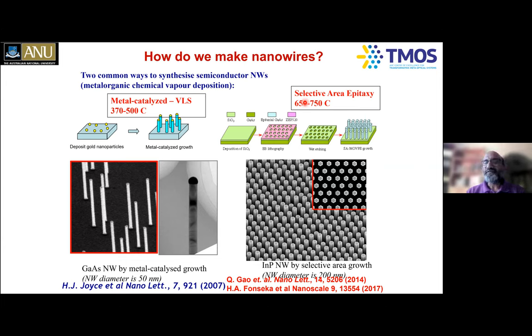In this case, I'm giving an example of indium phosphide. We take an indium phosphide substrate and deposit some silicon dioxide using plasma enhanced chemical vapor deposition, and spin coat the photoresist, and then do electron beam lithography and create patterns of holes. And then you etch through the silicon dioxide so that in these holes, indium phosphide crystal is exposed. Then you put this into the MOCVD reactor and heat it up to somewhere between 650 to 750 degrees Celsius and introduce the gases needed for the growth of indium phosphide, trimethylindium and phosphine. And then these gases dissociate and crystals start precipitating out. And now you can see you can create these ordered patterns of indium phosphide nanowires.